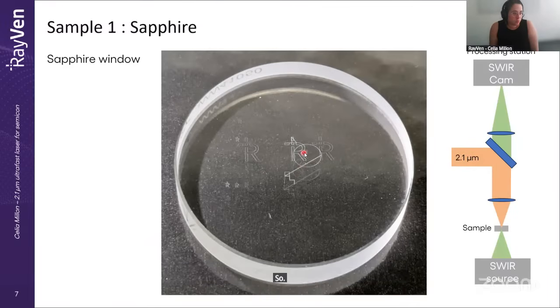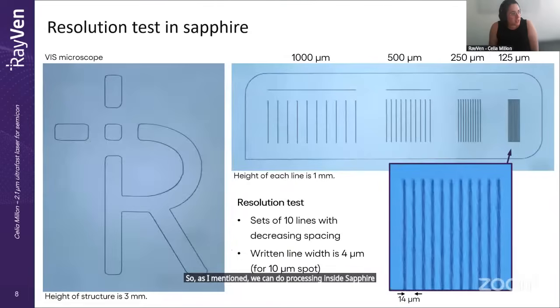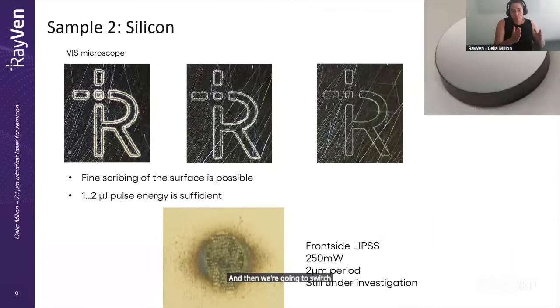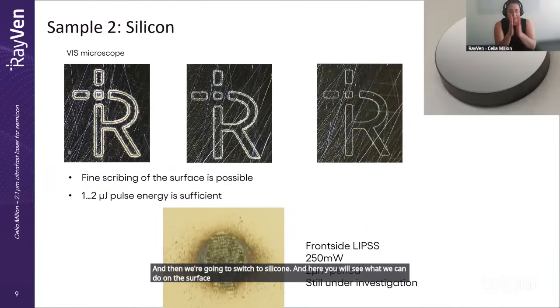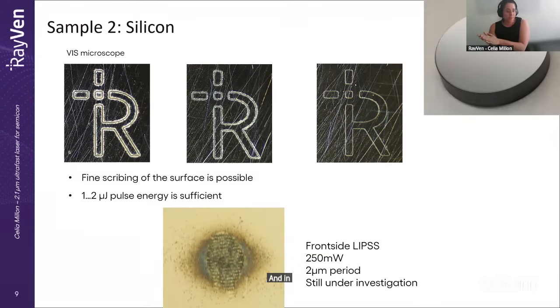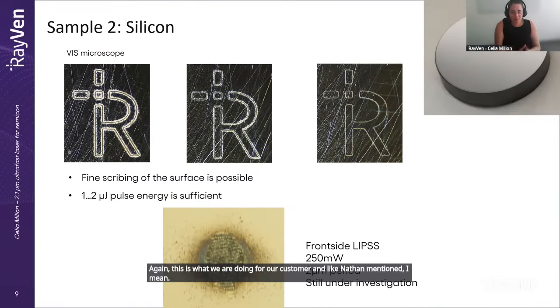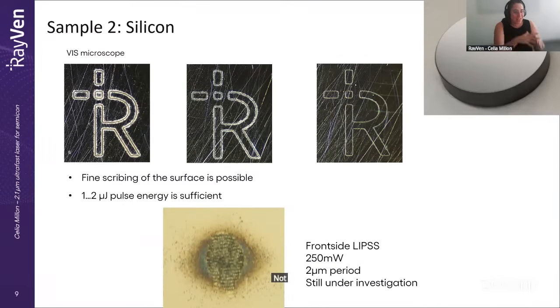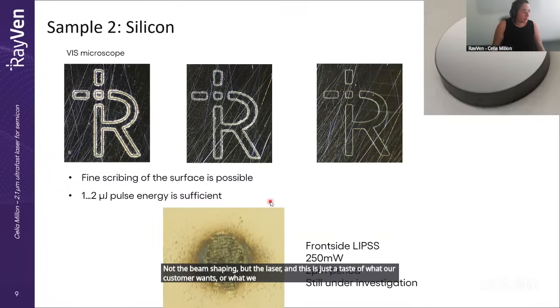As I mentioned, we can do processing inside sapphire. Here you can see a resolution test that we have made with a very clean structure. And then we're going to switch to silicon. And here you will see what we can do on the surface, in the volume, and in the backside. Again, this is what we are doing for our customers. And like Natan mentioned, we are providing not the beam shaping, but the laser. And this is just a taste of what our customers want or what we are doing for them.